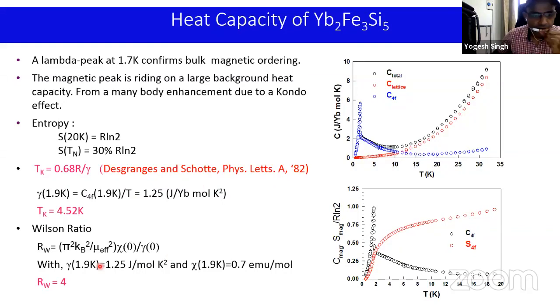To see if the material is correlated, one does what is called a Wilson ratio, which is just the ratio of the density of states seen in the susceptibility divided by the density of states seen in the heat capacity. And for normal metals, this is of order 1. And for Yb2Fe3Si5, we find 4. So this is a correlated material, clearly.